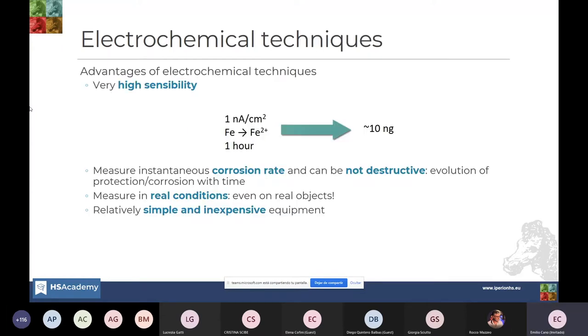These techniques have many advantages for measuring corrosion. A very relevant one is that these techniques are extremely sensitive. They have a very high sensitivity. So for instance, if we want to measure a corrosion process of the oxidation of iron to iron plus two during 1 hour, that is produced by 1 nanoampere per square centimeter, which is an intensity that sounds low, but it is quite easily measured by common laboratory equipment.